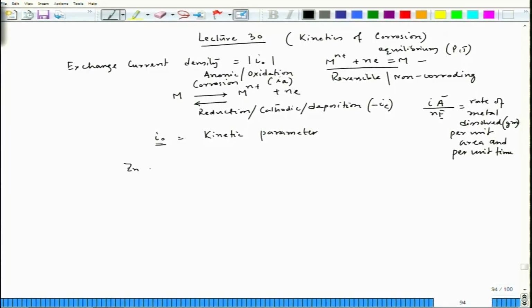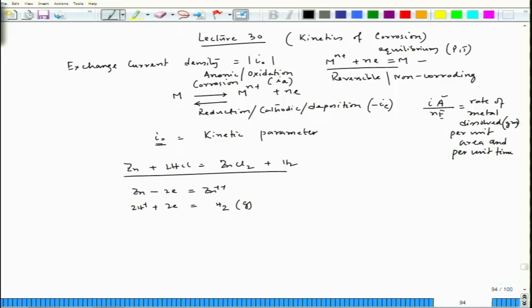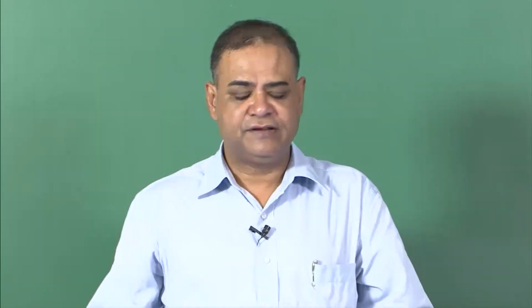For example, let us consider zinc plus HCl equal to zinc chloride plus H2. For this reaction it can be broken into two half cells. One is Zn minus 2e equal to Zn++, and 2H+ plus 2e equal to H2. This is the gas that forms on the zinc surface. Experimentally we have seen that when zinc is dipped in HCl, let us say pure HCl that does not contain any oxygen, so that means it is a deaerated solution, at that time we have these two half cell reactions.